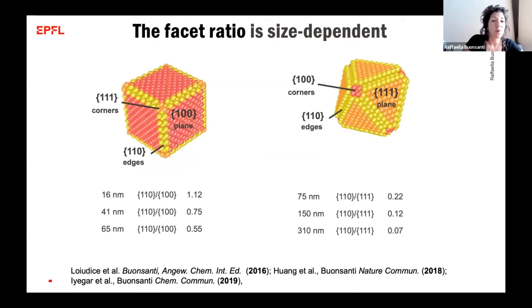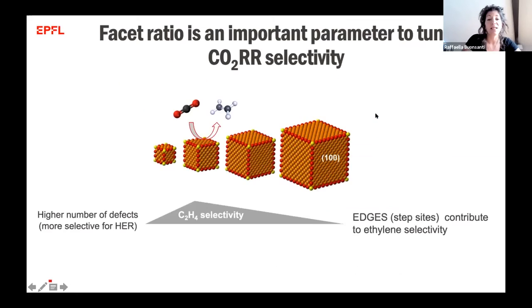So what changes when we change size is, of course, the surface to volume ratio, but this does not explain our findings. What instead changes is the ratio between planes. It's basically the ratio between the terraces and the steps. And so, what we found with the copper nanocubes and with the copper octahedra does confirm the selectivity of the 100 preferentially for ethylene and of the 111 preferentially for methane.